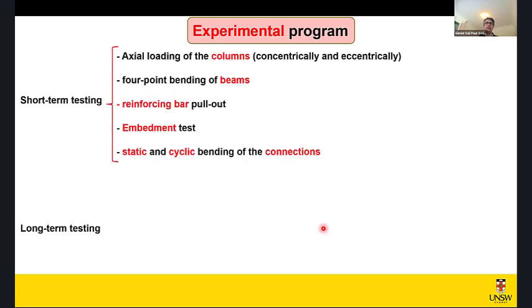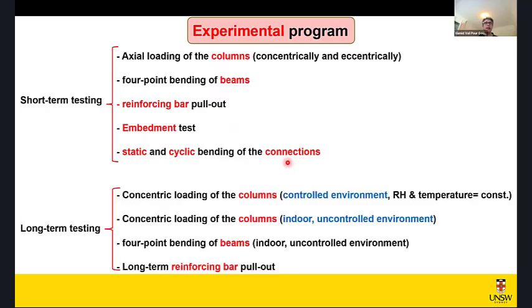In the short-term testing, we look at the axial loading capacity of the columns, four-point bending of the beams, reinforcing bar pull-out was also important, done embedment test, static and cyclic bending test on the connections to demonstrate the satisfactory performance in terms of stiffness, strength, and ductility, the three factors which initially I highlighted.